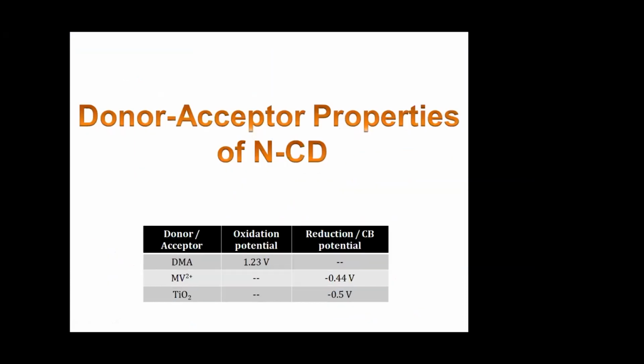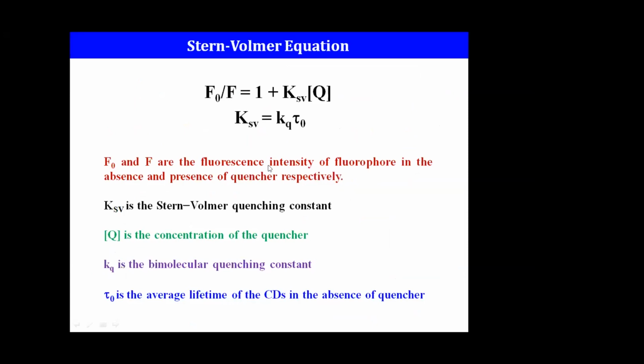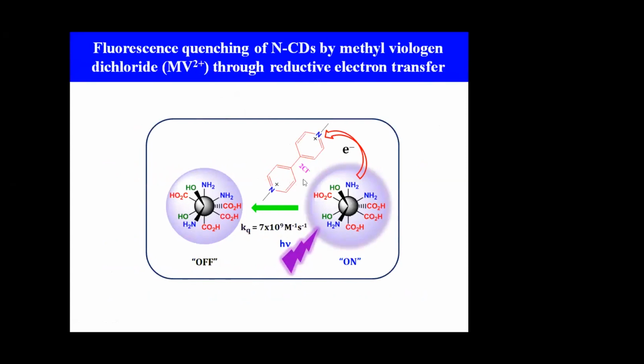Additionally, we have seen that there are donor-acceptor properties of these CDs, where nitrogen is present - nitrogen doped CDs we call it. So it works with - you can see the nice electron transfer reactions. You could really analyze the Stern-Volmer behavior, and you have the dynamic quenching behavior. This is because of the reaction of the excited state of the CD with methyl viologen. We have tested it, so you have a nice reductive electron transfer seen in this case.